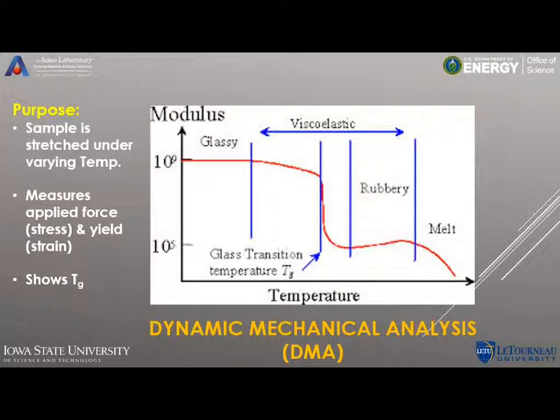When you take the plot of the strength modulus versus the temperature for a sample and stretch the sample over this range of temperature, you'll see a sudden point where the strength suddenly drops. That's where it's yielding, and that's the glass transition temperature.